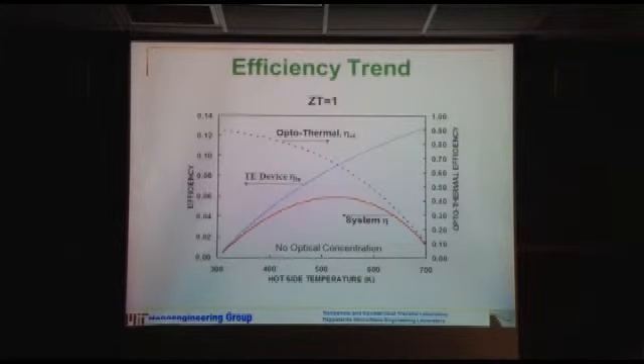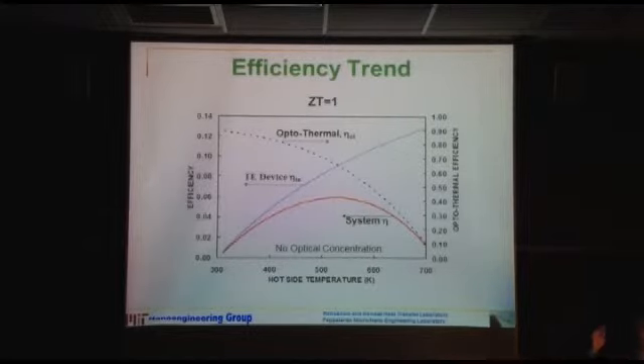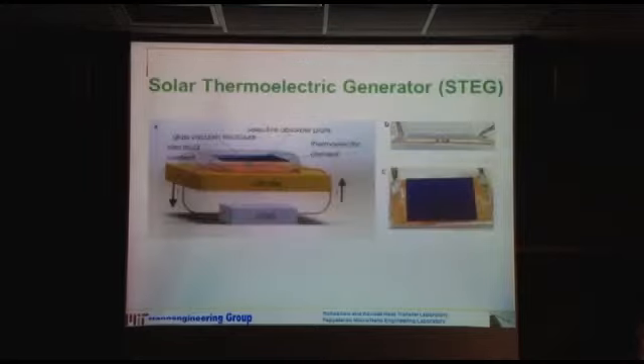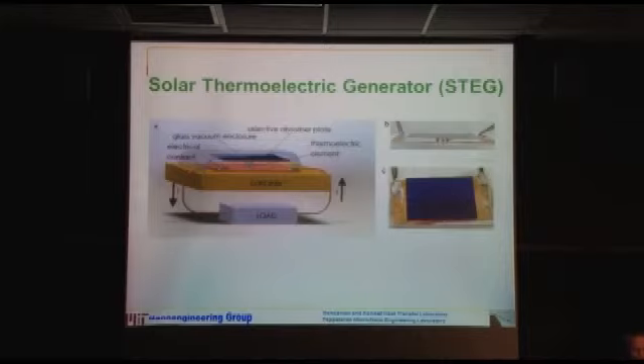So with that, we have some prediction of efficiency, and it's not very high with the current material, but it's very respectable, because when people look at solar, anything above 5-6%, people start to pay attention, because the amorphous silicon solar cell is also just in the 6-7% range. So this is a prototype we built. We have this absorber, and then we put the two small legs. That's our generator, and then we put it in vacuum.